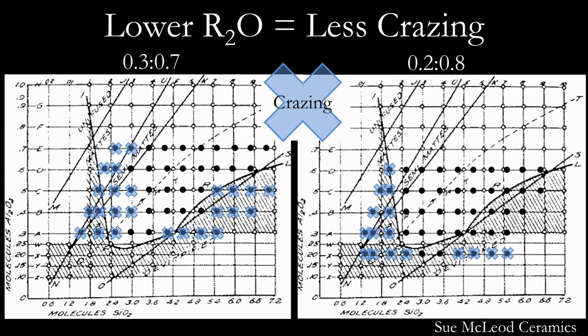A better way would be to take your crazed glaze and increase the silica and alumina so that their ratio stays the same, and you will move out of the crazing region while maintaining the surface quality of your glaze. Now, let's look at the far right-hand side of the map, the high silica region. Map number 2 has some, and map number 1 has quite a bit of crazing in this region. This is because unmelted silica has higher thermal expansion than melted silica, so these underfired tests are also crazed.